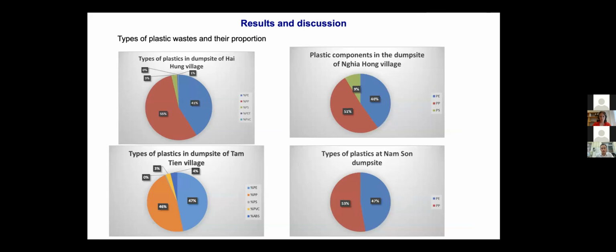For the dump sites and landfills, you can see their proportion increased a lot, for instance PE and PP with 55% in the dump sites and landfills. But we can see also the PET: we didn't observe the presence of PET in the dump sites and landfills, only a very small proportion in a dump site in Nam Định province. So that means that maybe a large proportion of the PET is already collected and separated for recycling before ending up in the dump sites and landfills.